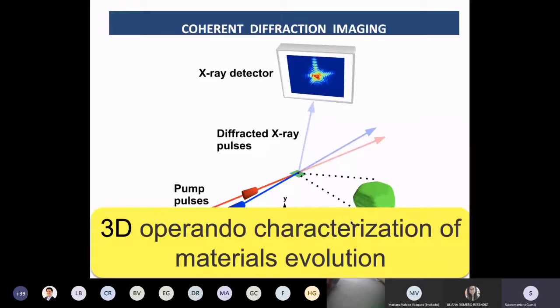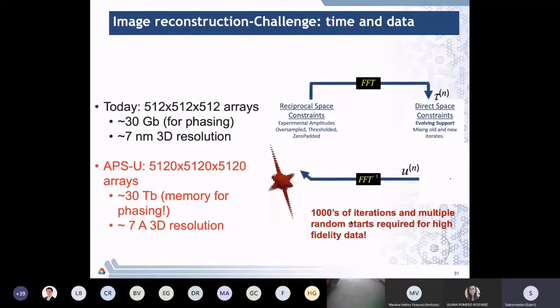The challenge with using these kind of X-ray or synchrotron facilities is that often a user will go to these synchrotron facilities, carry out their measurement, come back and analyze that data. There is a very tedious phase retrieval algorithm that is involved in reconstructing. So the idea is that in these experiments, one generally does not have information about the phase. And so what you do is that you only have information about the diffraction patterns, or you have reciprocal space information. Now you want to actually reconstruct this configuration from this reciprocal space information, and because you have no phase information but only intensity information, you are trying to actually follow an iterative procedure to come up with this reconstruction. That is very tedious, and that's why people actually almost always post-process their data.